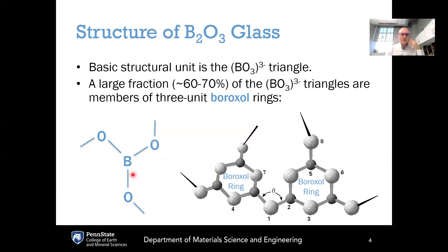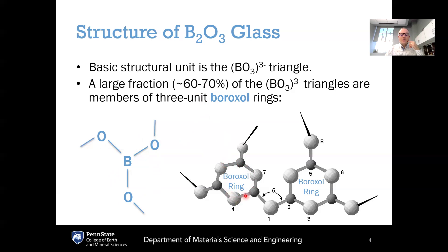In practice, a large fraction — about 60 to 70 percent — of those BO3 triangles are configured in three-membered boroxol rings. Taking three triangular units in a corner-sharing configuration forms a ring with three borons and three oxygens. About two-thirds of the borons are part of boroxol rings. So B2O3 glass has its short-range structure defined by the BO3 triangle, an intermediate-range structural feature defined by the boroxol ring, and no long-range order.